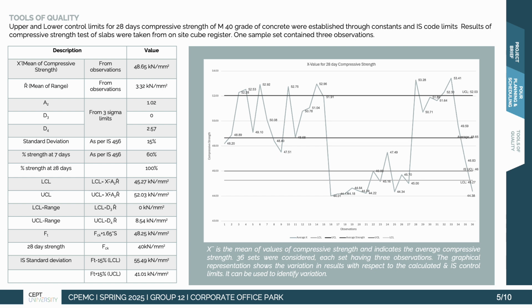So the straight lines are the upper control limits. The second one is the average, which was 48.65, which is X bar. And variation of the results is shown in the graph, with the lowest observation coming up to be 44.01 kilonewton per meter square, and the highest one coming up to be 53.41 kilonewton per meter square, which are all well above the desired compressive strength for M40 grade of concrete.